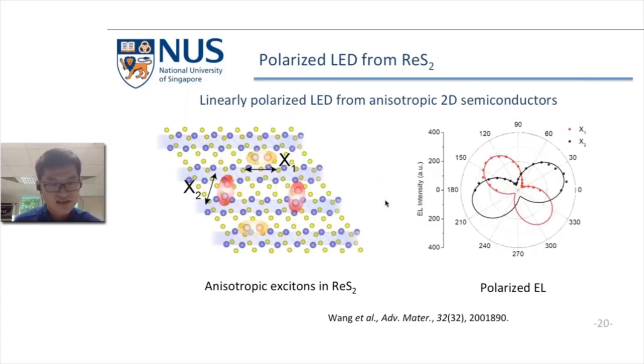In the last part on EL devices, I'd like to mention that for some 2D semiconductors with reduced in-plane symmetry, for example, in thin layer rhenium disulfide, excitons will behave quasi-one-dimensional. They have a preferred dipole orientation. For this type of 2D material, we fabricated devices and achieved light emission from the excitons. We find that the emission is highly linearly polarized. As can be seen from this figure, the two excitons show different dipole directions. This shows promise that 2D semiconductors with reduced in-plane symmetry can be used as on-chip polarized light emitters.